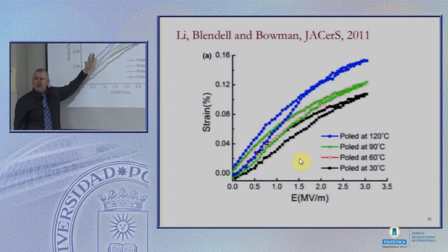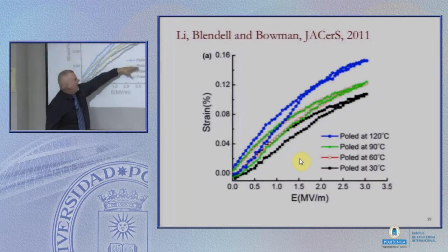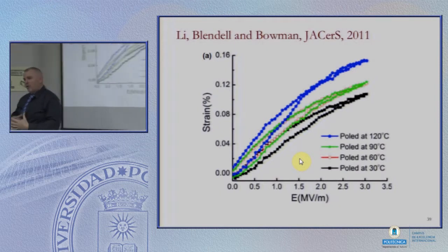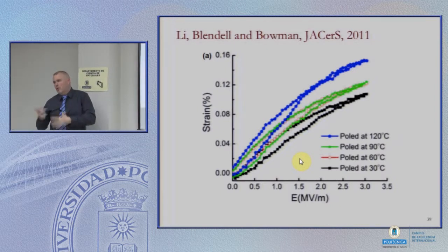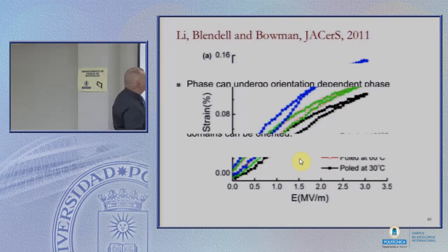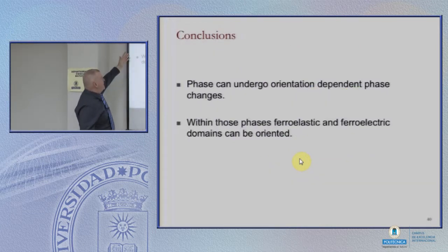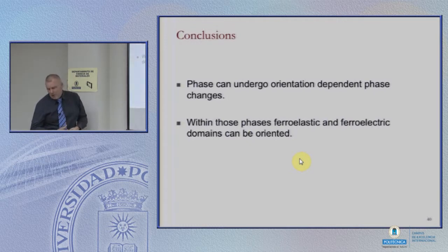And it makes a difference to do so, right? Even though at 90 C, it looks like it's all cubic, there is a residual effect of poling it at even higher temperatures. We've reproduced this recently several times on different compositions pretty close to this, but on either side of it. So there is a pretty strong effect. This is a stronger effect than we see in some of the other materials, or at least most of the other materials. The real conclusions from this piece of the presentation on BZT-BCT is phases can undergo orientation-dependent phase changes. And within those phases, both ferroelastic and ferroelectric domains can be oriented.